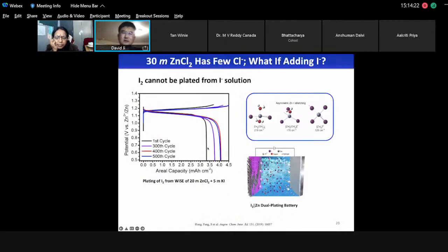So we had iodine in this case. We want to plate iodine, but if you have iodide in the electrolyte, you cannot plate iodine. Why? Because iodide will react with iodine to form triiodide. It's going to dissolve away. So the solution is we need to remove iodide from the electrolyte. We need to hide the iodide somewhere else.